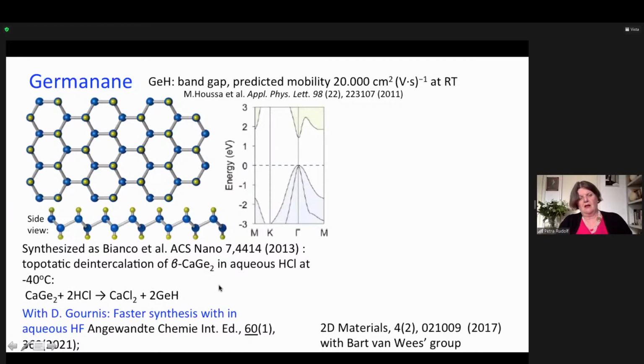I collaborated with Dimitris Gournis from the University of Ioannina to find a faster synthesis procedure. They found it, but then they characterized it together with my group, and we just published that in Angewandte. While the method published in 2013 takes about a week to get germanane, here it takes minutes. And then, of course, we use this material to try out several properties.